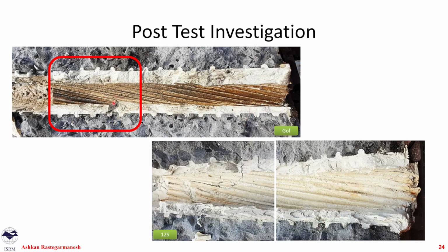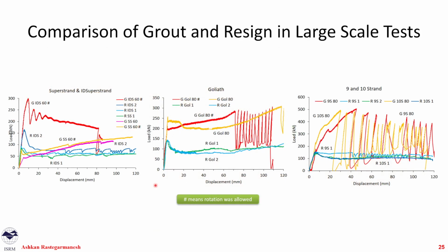We see very sharp edges and very good lugs. So we call these lugs, or ridges in between them, at the entry point. But towards the collar, we see more damage. But obviously, because the resin is more ductile, we are seeing less of a crater. And in the bottom, we see another example of having more damage towards the top. And as we go towards the end, we see less damage.